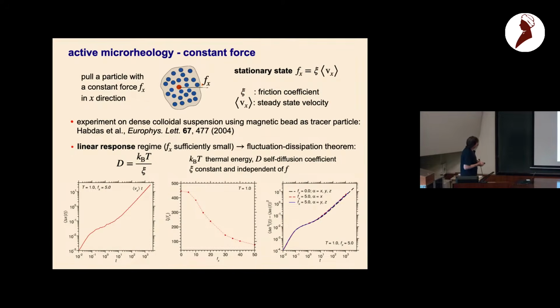And so here I show examples, here and here, where we are in the linear response regime. This is the displacement as a function of time, at temperature 1, force 5. So if we wait long enough, we approach the stationary regime from which we can read off the mean velocity, the average velocity.